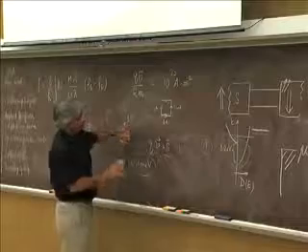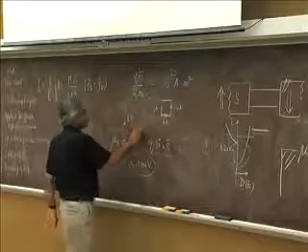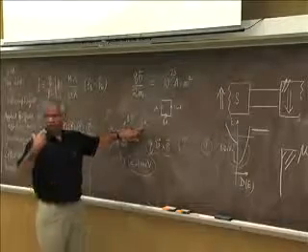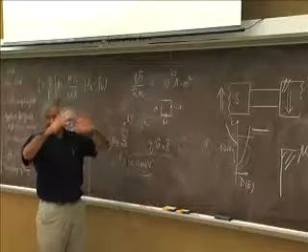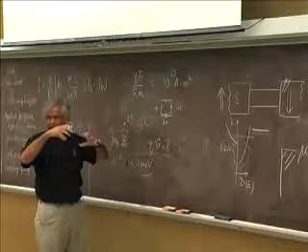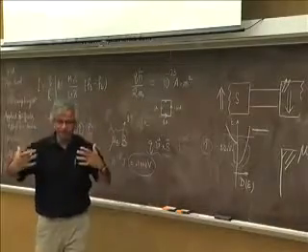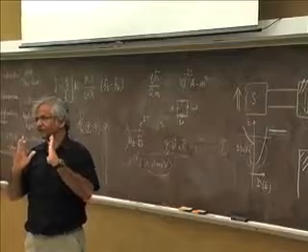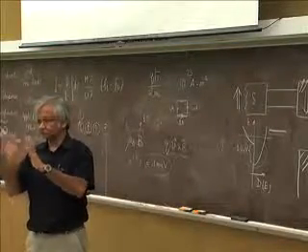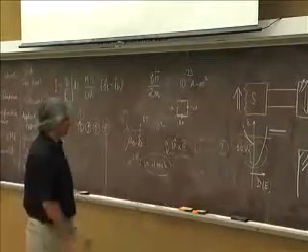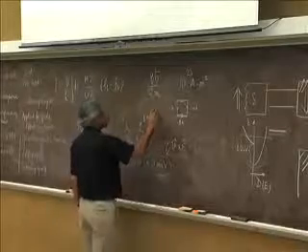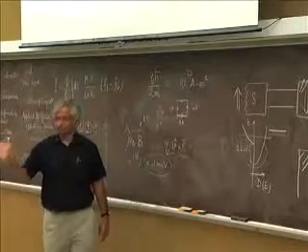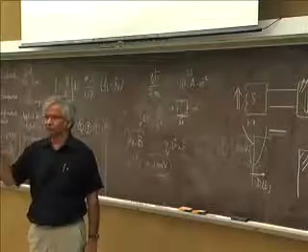You see, ordinarily it would have been feeling this 10 to the 4th Tesla. Normally you have spins there that's like 1 on every atom, let's say. But what you have done is created an imbalance that's like 1 part in a million. Well, then instead of 10 to the 4th Tesla, you'd have 10 to the minus 2 Tesla, which is 100 Gauss, and that's enough to turn a magnet. That's the kind of field you need to turn a magnet, basically.